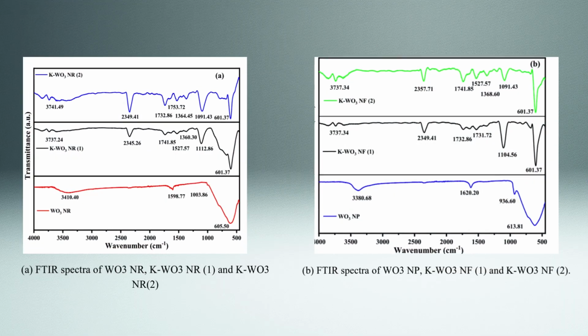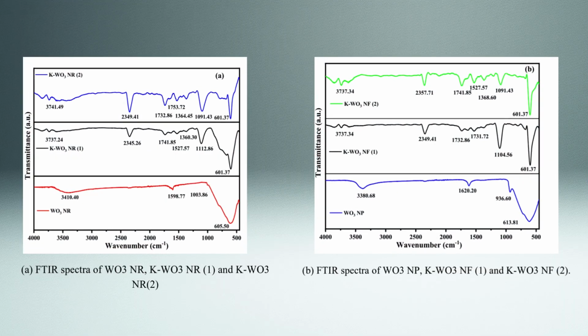The FTIR spectrograph confirmed the successful synthesis of the WO3 material by showing the characteristic W-O-W bond below 1000 cm inverse in all samples. Differences in the high frequency region of the doped materials indicate that potassium has successfully modified the chemical structure, likely due to the incorporation of potassium ions or the resulting changes in the surface groups.